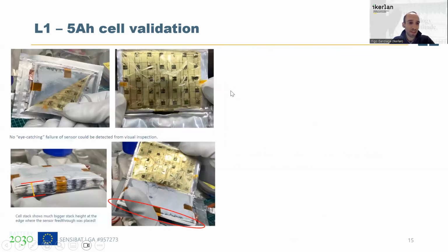We did a postmortem analysis, and we saw that there is no failure of the sensor itself. So the problem was just here in the area where the sensor feed-through is placed. So it seems that the glue that we put here to seal the cell has an impact on the sensor, and with time it deteriorates and the electrolyte gets inside the sensor.